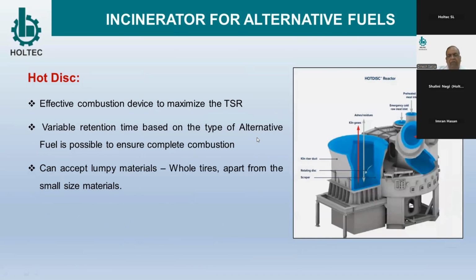Another option, which has been available for a very long time, is a hot disc, which is again for a high TSR rate, and we have the facility for using bigger size material and lumpy material. So it does not impact our core process, that is the pyro process, and gives minimum hindrance in the main process, and our disturbances get reduced.